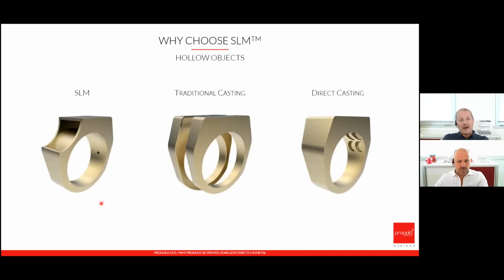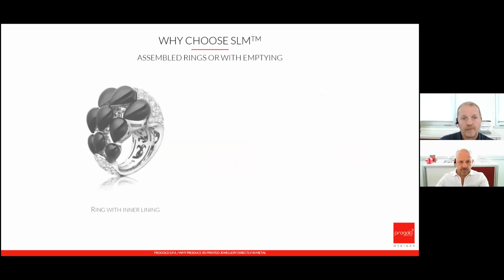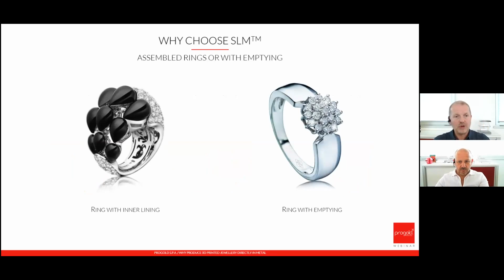As I told you before, SLM allows to create large hollow objects. The picture here shows a cut, but is just to show the part inside, okay? Only 2 very small holes are required to evacuate powder in the parts. Traditional casting instead requires 2 or more parts assembly and soldering. On the right, direct casting requires gates to evacuate investment. Here we have 2 casted rings. Geometries are not particularly suitable for SLM, but help to point out some casting requirements we might overcome with SLM.